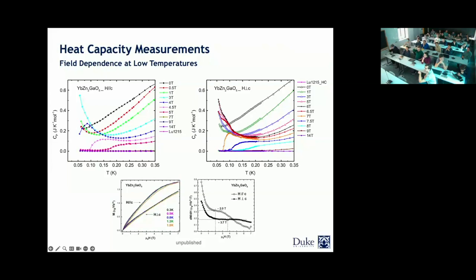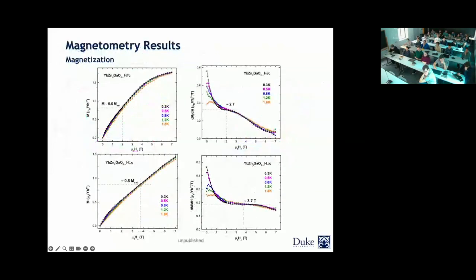The change of behavior for the 2 different orientations as a function of field agrees with what we are seeing in our dM/dH at very low temperatures. We were not able to go to lower temperatures, but I'm guessing that if we went even lower, we would be able to see this a little better. This is just the temperature dependence of it so that you can see it better. One key point is that when you have a triangular lattice and you see a plateau or a change in the line shape, most likely it's going to be the 1/3 plateau for triangular lattices.